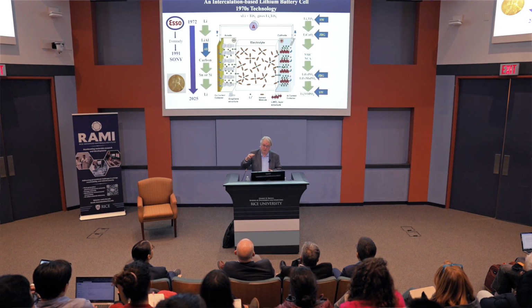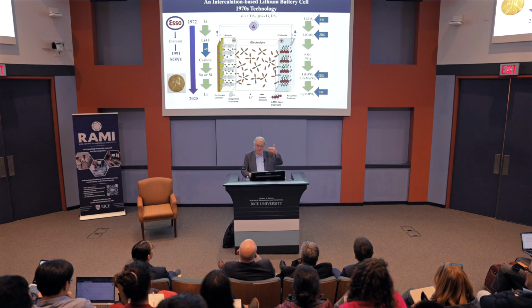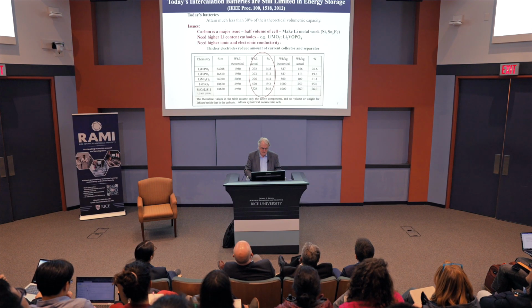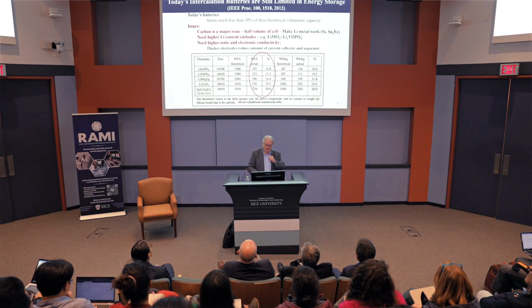It has a higher voltage, but both these you'll see in a moment are very low energy density compared with the oxides. So we decided if we want to increase the energy density, why don't we put 2 lithiums in or 2 sodiums, which means we had to go away from iron, and we've switched to vanadium. I'll show you one slide later on, because vanadium can go from +5 to +3. So here's the